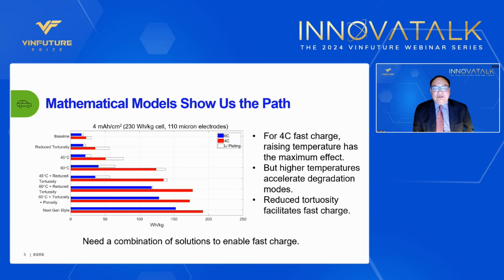The next row is you perform the fast charge at 45 degrees C. You can see it getting better. And at 60 degrees C, it's getting better. And then you do 45C with reduced tortuosity, it gets even better. And 60 degrees C plus reduced tortuosity, it gets even better. And so on and so on. And finally, with a new generation of electrolyte, it gets the most specific energy, almost 180 to 160 watt-hour per kilogram, depending on what rates you want to charge. Some of the noting here is you can see that at the 4C fast charge rate, raising temperature had the maximum effect. So that's one point you want to take into account.